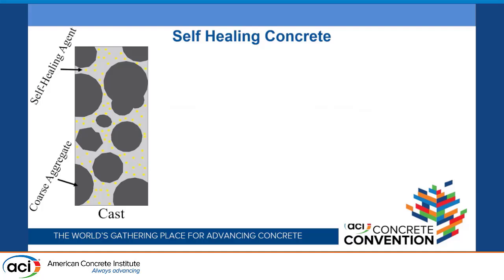If you're not aware of self-healing, there's two main mechanisms in concrete. You have your autogenous self-healing, which comes from rehydration of unhydrated cement paste after cracking occurs. That's generally on the smaller scale, looking at microns of self-healing, but is important to recognize for general structures.